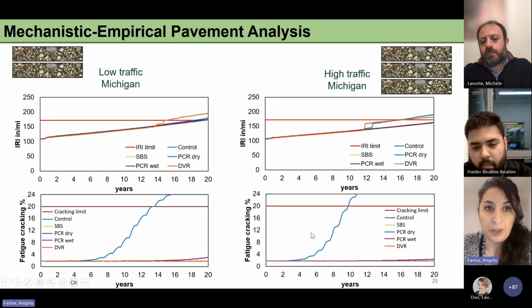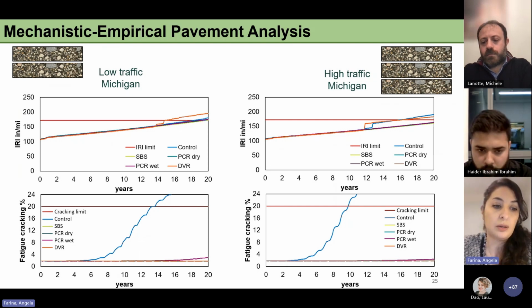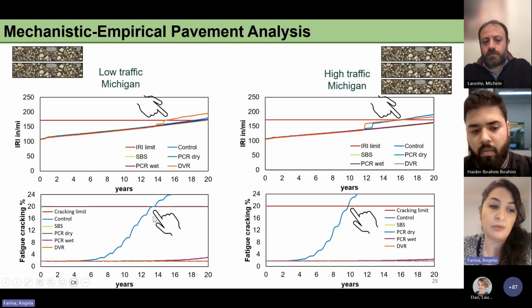For the mechanistic empirical analysis, we found that all the mixtures showed a failure for the IRI before any other distress, except for the control mix that failed for fatigue cracking first. So the number of the reconstruction were calculated based on these two parameters.